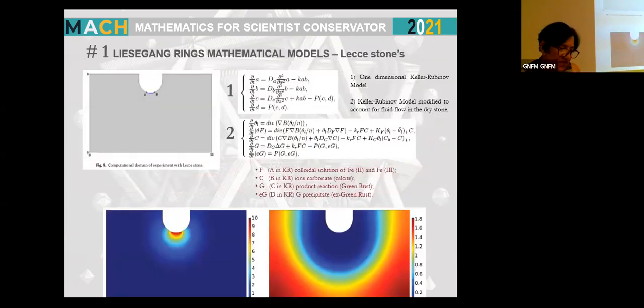To describe the process of precipitation of iron in Lecce stones, we propose a mathematical model that is a modification of the Keller-Rubinov model, where the precipitation function is replaced by a smooth function to avoid the instability of the model. In such a way, we were able to develop a simulation algorithm capturing the main features of the phenomenon of Liesegang formation in the stone. The shape and intensity of rings depend on the nearness to the iron source, as shown in the laboratory experiment, where the presence, shape, and position of the rings are highly influenced by the physical contact between the stone and the iron nail.